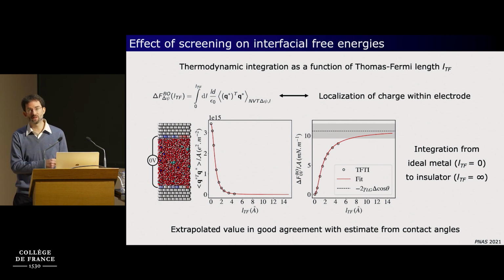And what is important is that it correlates the interfacial free energy with the localization of charge within the electrode. So here is, again, for this gold aqueous solution electrolyte capacitor, the integrand, and this is the free energy as a function of the Thomas Fermi length. The symbols are simulation results of this Thomas Fermi thermodynamic integration. The line is a fit, which is inspired by the models that I'm going to describe on the next slide.